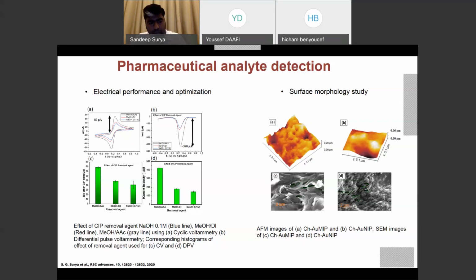And the same in the bottom, the corresponding bar graphs show the same data in terms of oxidation current peaks and reduction current peaks for CV and DPV. So one can easily identify the highest current has been achieved for methanol and acetic acid here. Further, the surface morphological studies have been carried out between the molecularly imprinted polymer and non-molecularly imprinted polymer, the differences. Here one can easily see from the atomic force microscopy the highest peaks and valleys recorded for the MIP, whereas in the case of NIP, we have seen very smooth surface as compared to MIP.